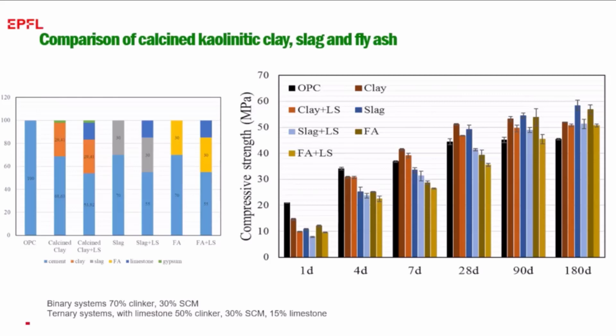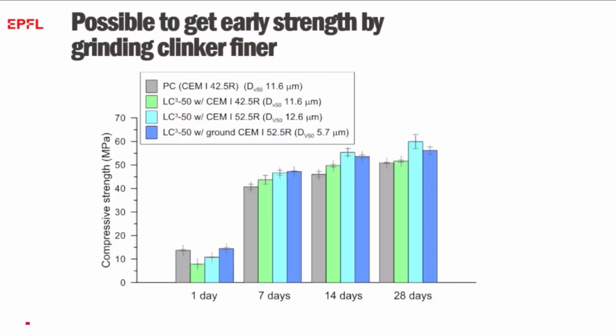But the big advantage of the calcined clay is that we develop the strength much earlier. Particularly, we have pretty comparable results between the binary blend with just 30% replacement and the ternary blend with 50% replacement. And these stay ahead of the reference at 7 days, whereas the limestone addition tends to have much more impact on the mixtures with slag and fly ash, because the alumina in those materials is not so readily available. They're much more slow reacting materials.